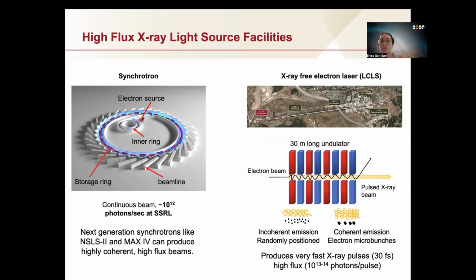The other option, when you actually cannot use a continuous beam, so if your sample is highly sensitive to radiation or you're trying to look at very fast time points, you can use an X-ray free electron laser. So rather than having a storage ring of an electron beam, you have an electron beam that is produced at an electron gun way down, at least a kilometer away from your experiment. And the electron beam is then accelerated through a very long quadrupole magnet undulator, 30 meters long in the case of the Linac Coherent Light Source at SLAC.